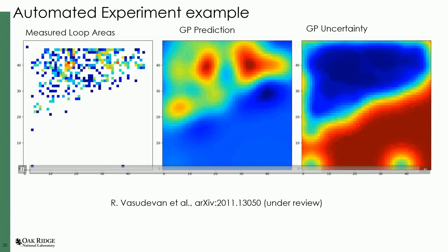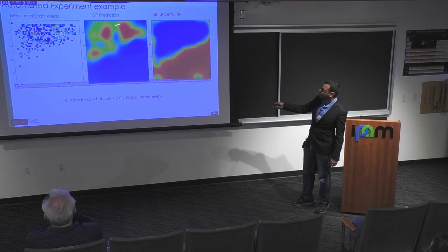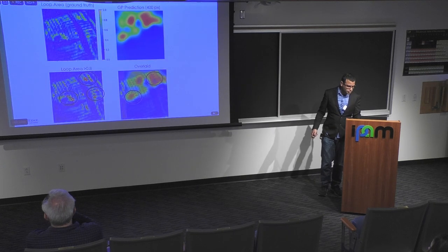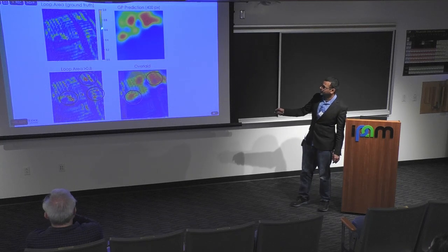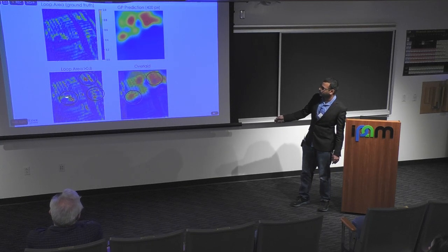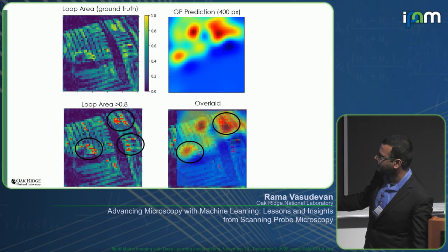What you see is that the sampling points will be around the places where the GP prediction is high. If we compare this to a ground truth, it indeed does find regions where, based on the ground truth, the spectra had maximum area, which is what we were after. But you also see that there's a problem with this. If you look at the ground truth versus the reconstruction from our optimization, it's very poor, to be honest. We're not capturing any of the image structure.